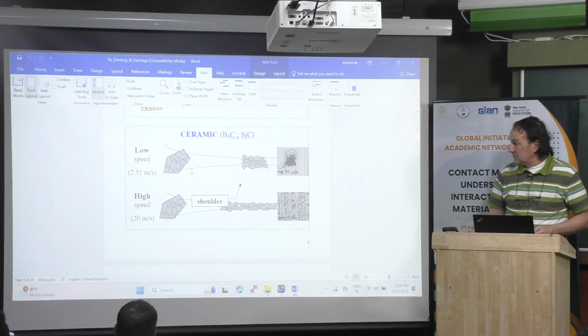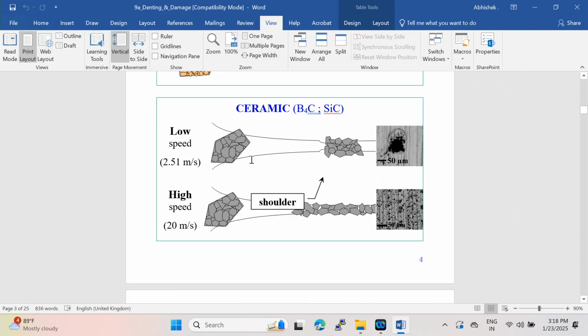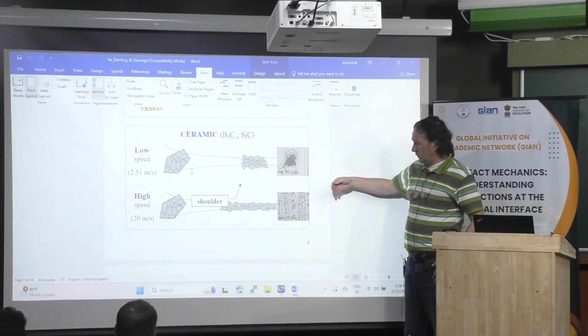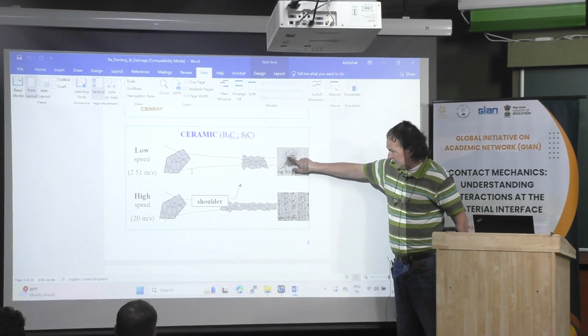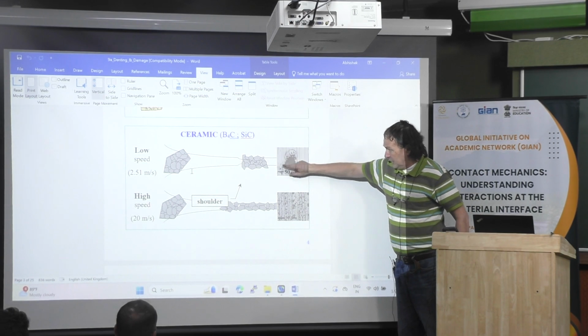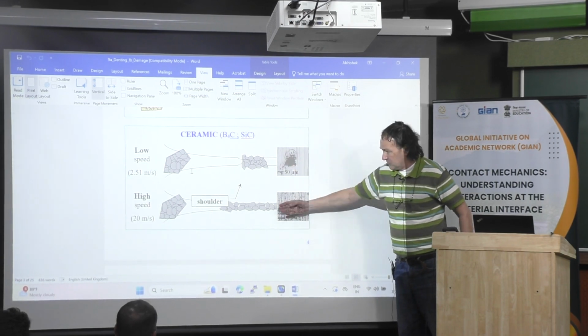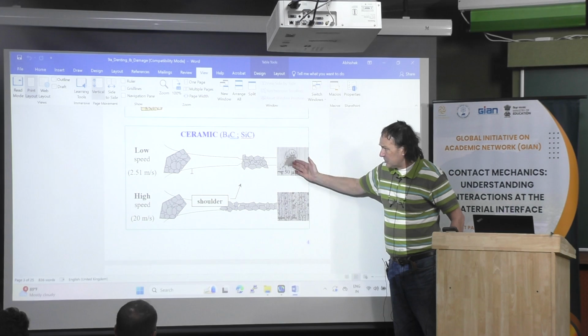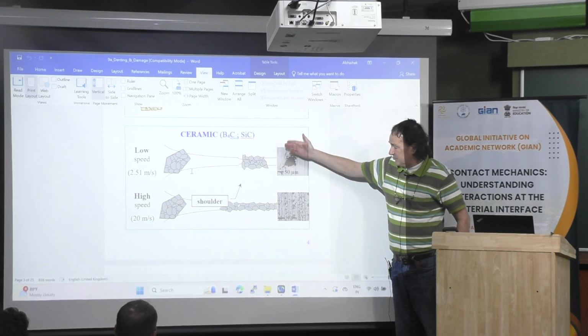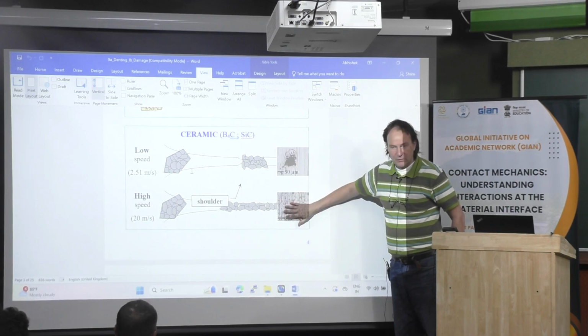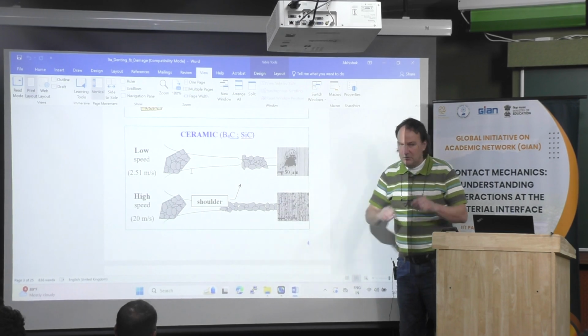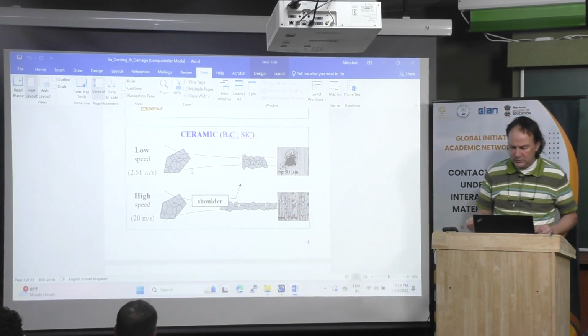And these are also done with ceramic. Then boron carbide and silicon carbide. These are real dents that we observe in our experiments. You can see the size here with many small particles around, and this is with the same ceramic materials but at high speed. Then you crush everything. So you have many small dents.